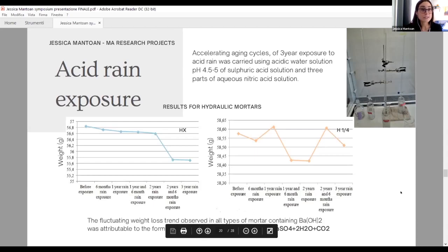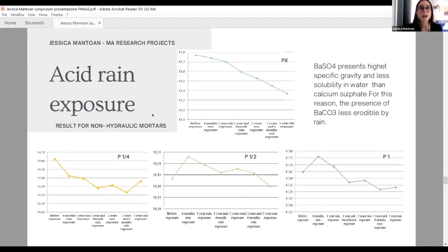And its formation is really interesting because, differently from the decay product of calcium carbonate, which is calcium sulfate, highly soluble in water, barium sulfate is completely insoluble in water. So its formation corresponds to a new material that is no longer soluble in water, creating in a way an increase in weight. A similar result is also visible for non-hydraulic mortar. For our sample without any additive, the trend of the weight loss is constant, and the material lost is quite a lot. While for our mortar containing barium hydroxide, we can see that the trend is going up and down. And finally, due to the formation of barium sulfate, we have much less weight loss.